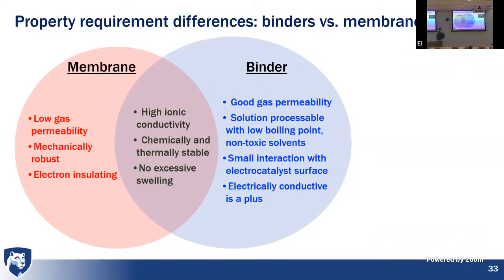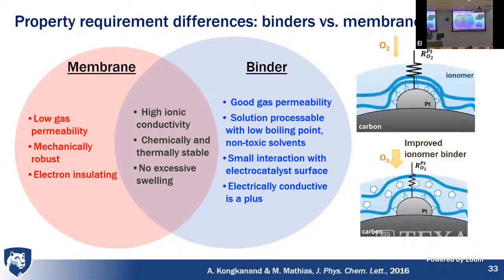And then you want to be able to process these electrodes with non-toxic solvents, technically. You don't want the chemistry in these binders to interact with the electrocatalyst surface. And you actually need to move electrons around in the electrode, so being electrically conductive is a bonus. And so this is a paper by General Motors talking about the importance of these binders. If you could get a binder that had fewer anions to adsorb to the surface and was like Swiss cheese, where it allowed the gas to go through, that would be advantageous.